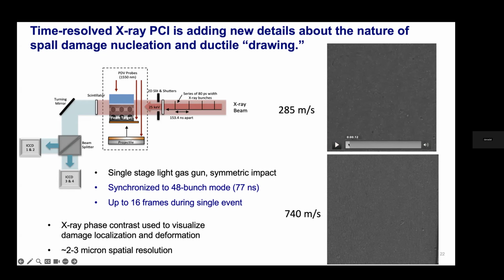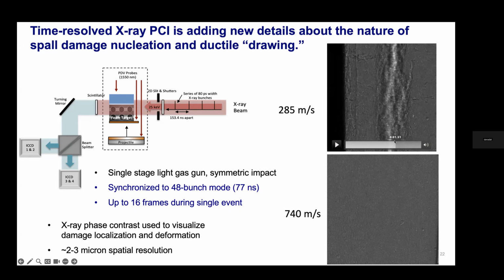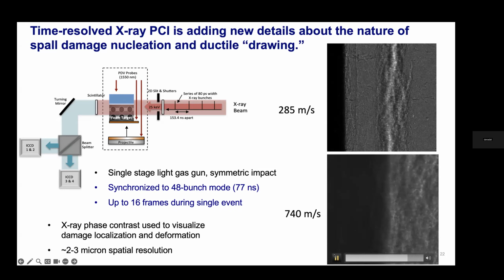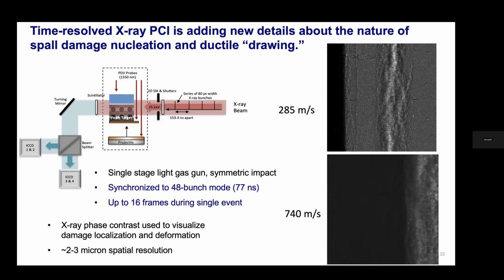So this is one of the polymers that we've now shocked. The shock wave has actually gone through the sample. And if you look, like in this frame, you start to see evidence of the damage forming in the material. It's very difficult, you can see it by eye, it's very difficult to threshold and detect. And then what you see is over time, it just ductilely draws. And so you get this very wide damage plane in the material, and then it basically just draws that whole plane apart. So it's quite a large damage plane. And if you go up to higher velocities, the whole polymer basically falls apart like that.